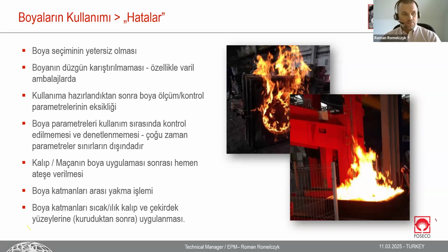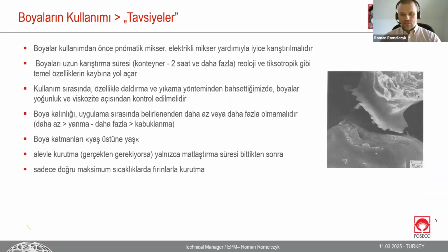That's it. Another very important point: when we need to apply 2-3 layers of the coating, it is very important that the coating is applied wet on wet to prevent scabbing, to give a chance that the coating will, with each layer, stick together very strongly. So the advice is nothing more than the opposite of what I showed before. We need to control and take care about wet on wet layer application. Drying by flame, but only if it's really needed. This is the first point.